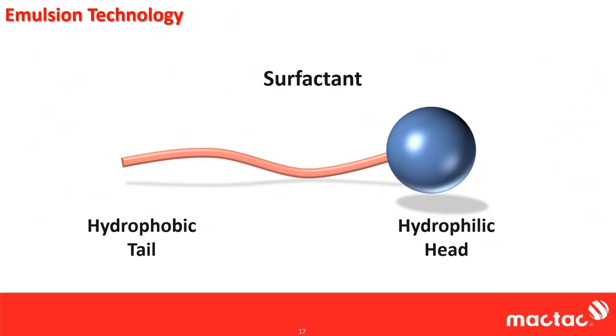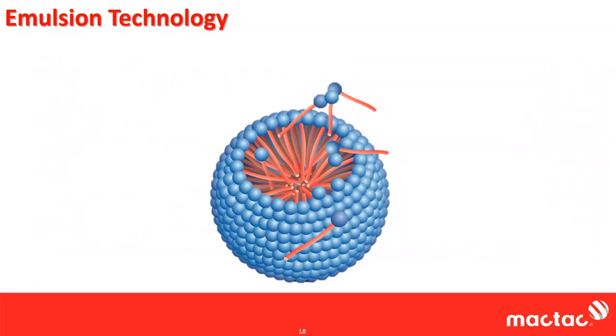So they're based off of surfactant. Surfactant is the main component of what we call soap, and they're unique polymers. The way that soap, or surfactant in this case for adhesives, works is that a surfactant is a molecule that has a hydrophobic tail and a hydrophilic head. So basically the tail hates water, loves oil, and the head loves water, hates oil. And because of that duality, this is how you get oil to mix in the water. What you do is when you put them in the water, they form this. Since we're talking water-based adhesives, all the hydrophilic heads are going to be facing out, and all the hydrophobic tails are going to be facing in, and they form what's known as a micelle.